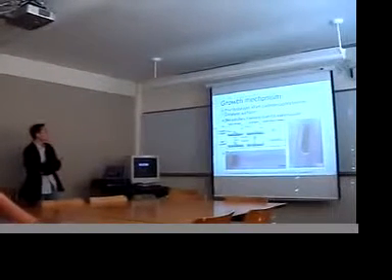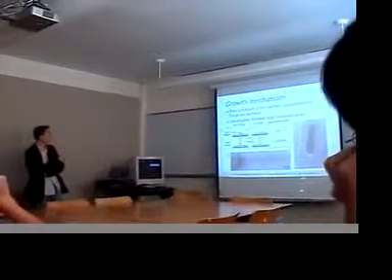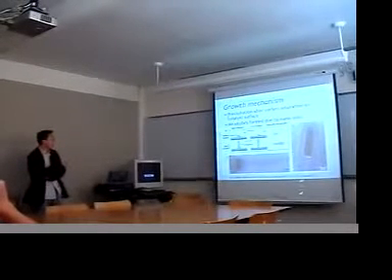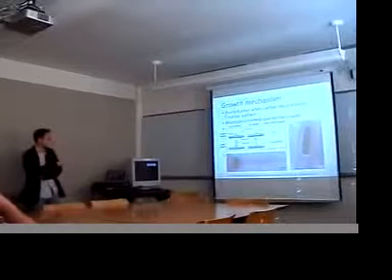We also observe two different kinds of growth mechanism. For CVD, typically we have a base and tip growth mechanism, whereby the carbon atoms from the precursor gas are absorbed into the catalyst. Once the catalyst is fully saturated with carbon atoms, the carbon nanotube will start growing up. You can have both cases, where the catalyst is still attached to the substrate, or where the catalyst is pushed out at the tip. So these are TEM images taken. You can see that this catalyst is at the base, and this catalyst is at the tip.